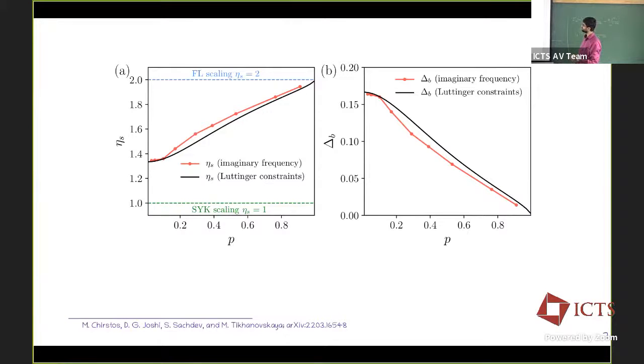The lower curve is actual numerical data that you obtain by solving fully the saddle point equations at finite temperature and taking the limit T going to 0. So this black curve is exactly at T equals 0. This red curve with dots is obtained by solving the saddle point equation at finite temperature. So we solve in Matsubara space, which we can do only at finite temperature. And then we look at the low temperature limit, what's the value of delta B. And as you can see, the two agree pretty well.